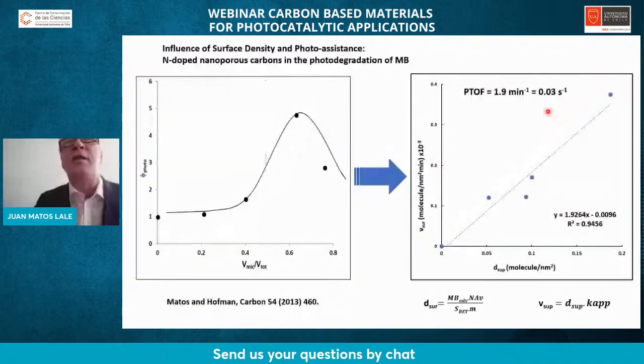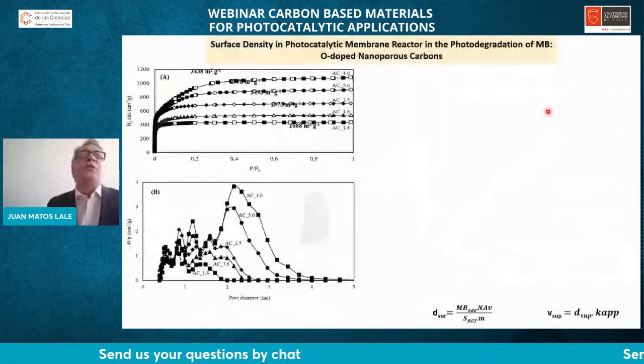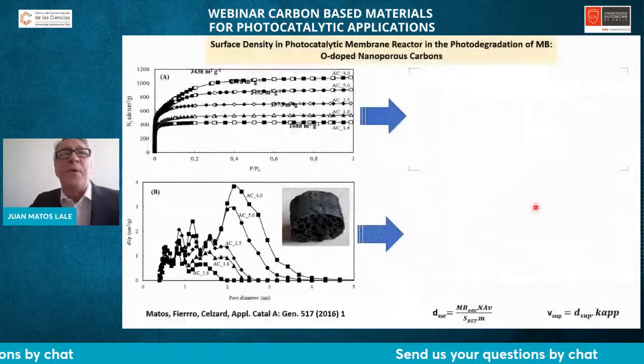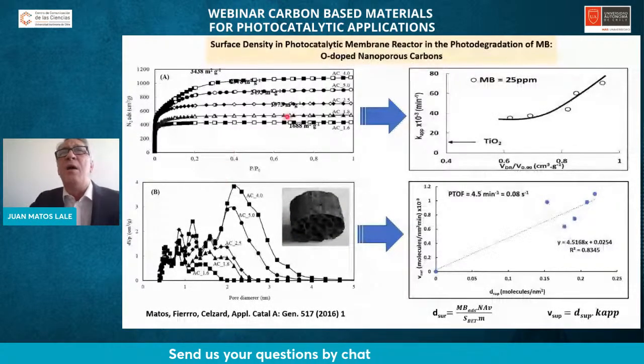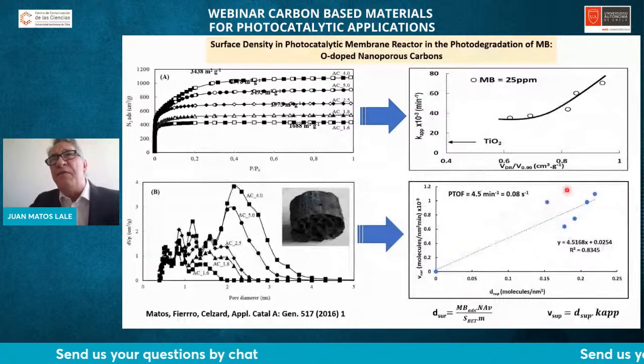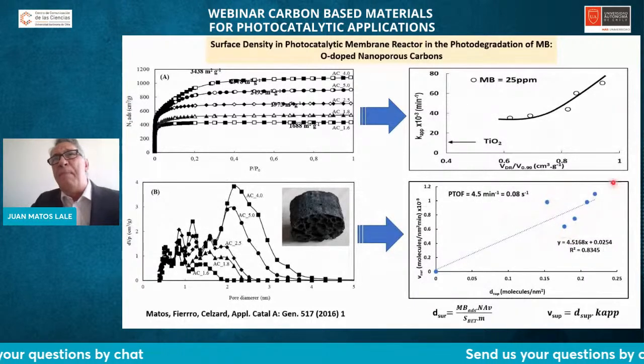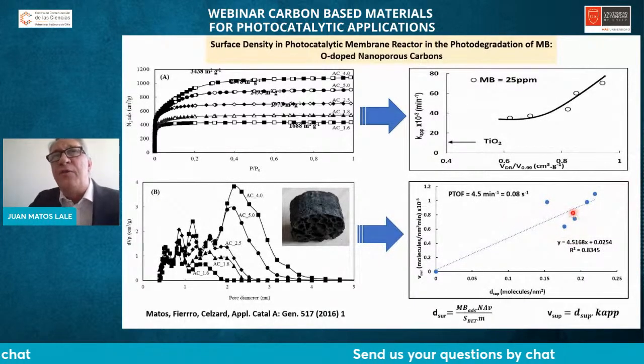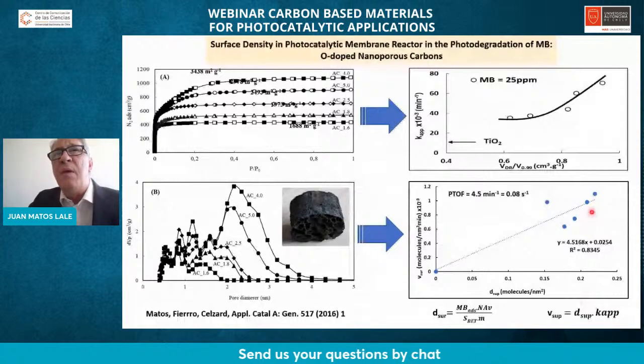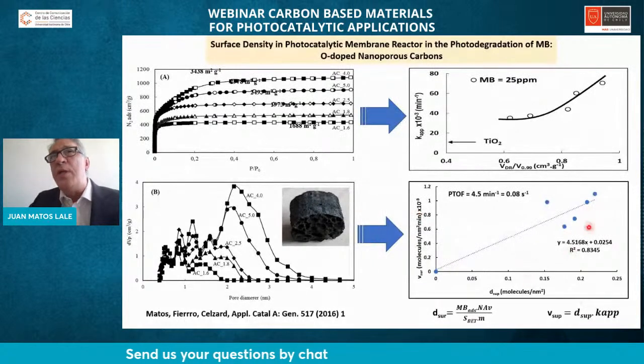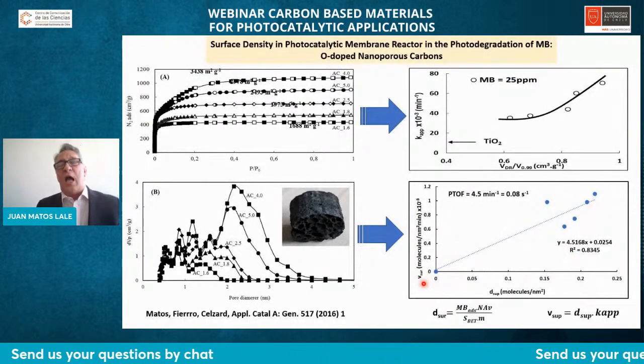For the case of oxygen-containing or oxygen-doped carbon, we also achieve a very interesting relationship for different kinds of high surface area nanoporous materials. And we achieve an interesting point in this part between the surface density and the surface reaction rate.